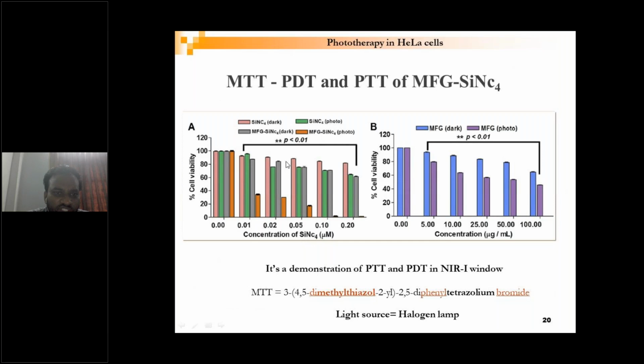Whereas you can see MFG SiNC4 is also not very effective in the dark, but when you illuminate it with NIR light, you see a decrease in the survival rate of the cells. Even at 0.20 micromolar, SiNC4 on top of MFG has very good therapeutic results. See here, they almost have zero survival rate. This is the combination of photothermal therapy and photodynamic therapy in dark and light.